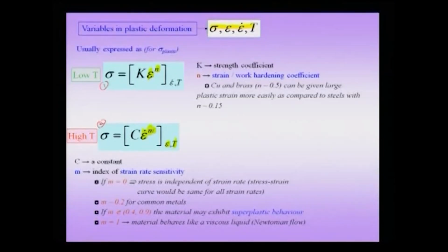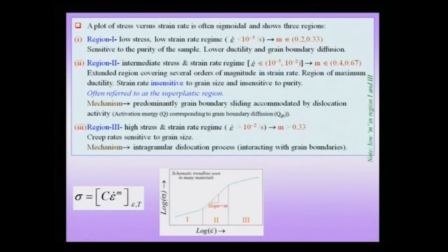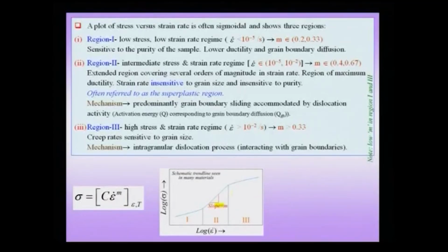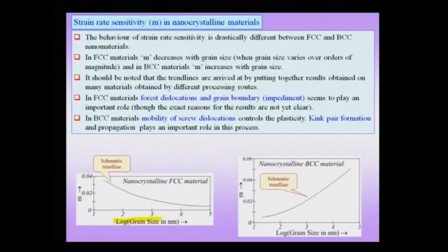Therefore, at high temperatures the strain rate sensitivity becomes an important parameter, and we had noted that when you have a high strain rate sensitivity, we typically expect superplastic behavior. We had seen examples of this high strain rate sensitivity in superplastic deformation, and we had noted that in the case of superplasticity, the region with high strain rate sensitivity, like between 0.4 and 0.67, is referred to as the superplastic regime in a log stress versus strain rate plot. So, this is where you get extensive superplastic deformation, and this is the region of high strain rate sensitivity.